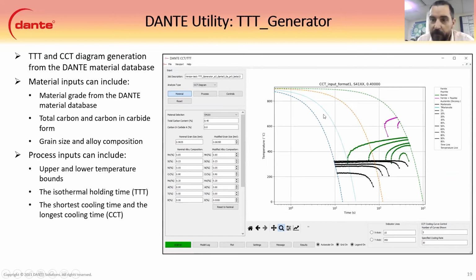We specified one at 20 degrees C here. Yep, 30 degrees. 30 degrees C per second here. And so that's this rate here. And if we cool at that rate, then we miss the bainite nose here, and then we hit just the martensite, which is kind of what we were going for. And so that's the TTT generator.